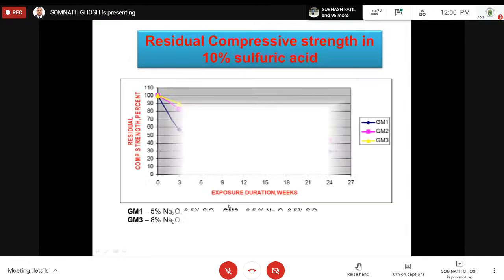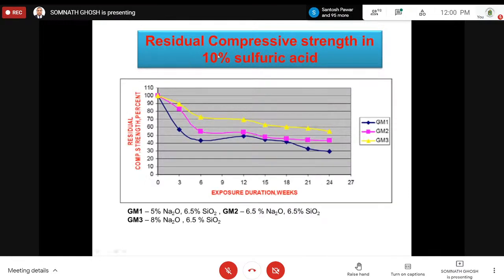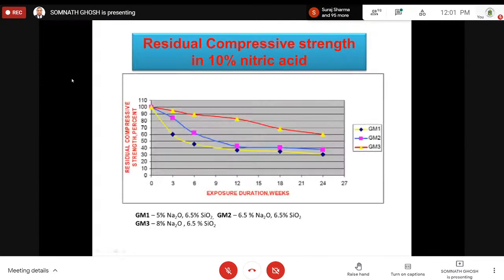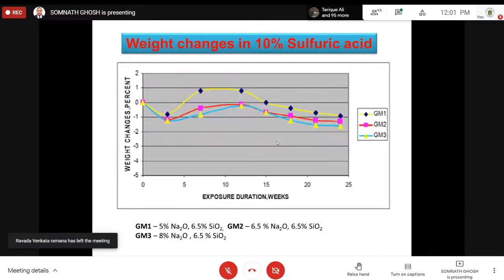So these are the tests you should perform. And if you immerse the specimen in 10% sulfuric acid, then how the strength is decreasing, with the number of weeks: 3, 6, 9, we did it up to 24. Now people are doing much more. Now this is with nitric acid. Previously sulfuric acid, now nitric acid. This is the weight change in case of sulfuric acid.